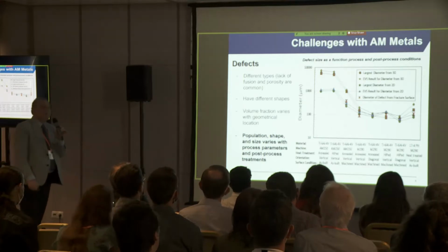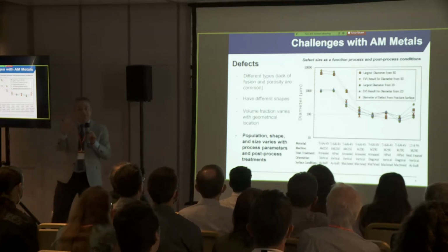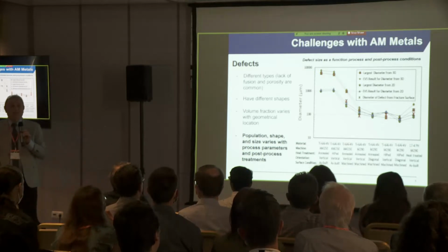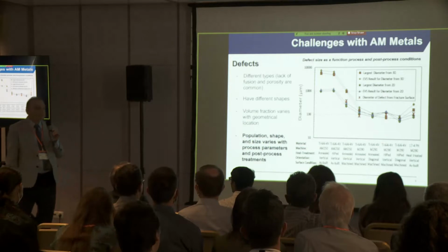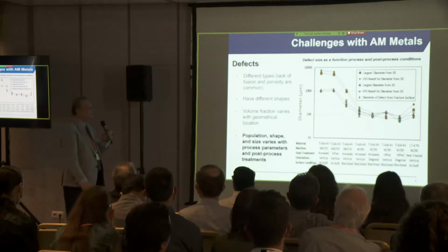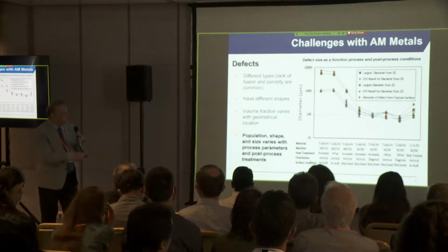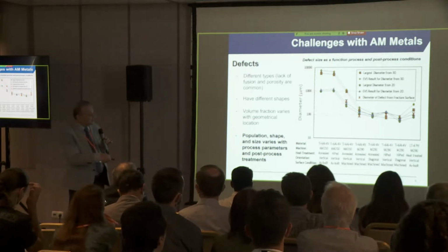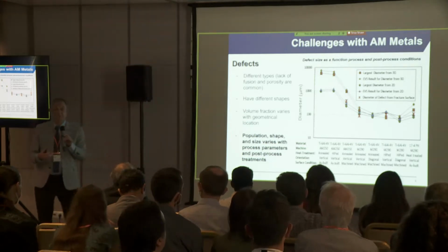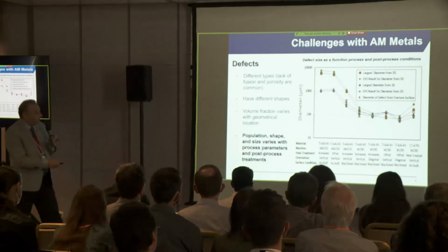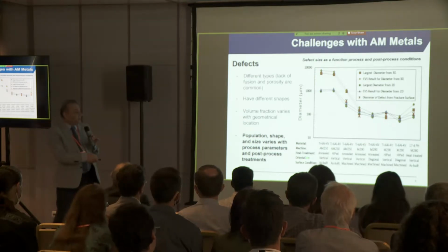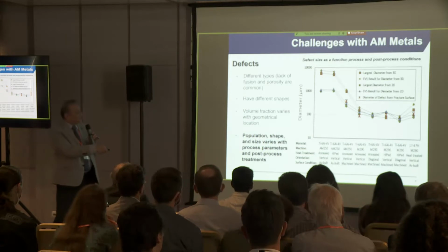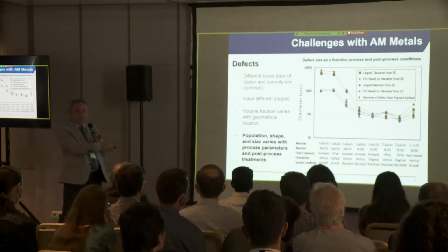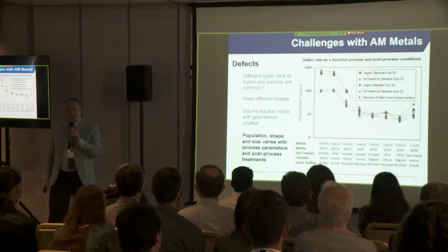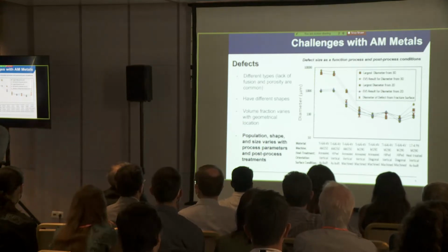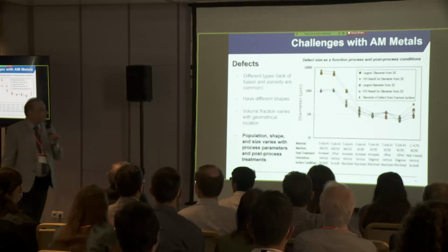There are many, many process parameters in additive manufacturing. Some count close to 200 of them. There are many post-process procedures that can be used. As a result, there is a lot of variations in defect sizes and populations. So for Ti-64, depending on what kind of machine, additive manufacturing machine was used to build the material, what kind of heat treatment was conducted, what kind of orientation the build was, you can see the size of defects changing quite a bit. And this is logarithmic scale. So we are talking about not a factor of 2 or 3. We are talking about orders of magnitude difference in the nature of the defects.